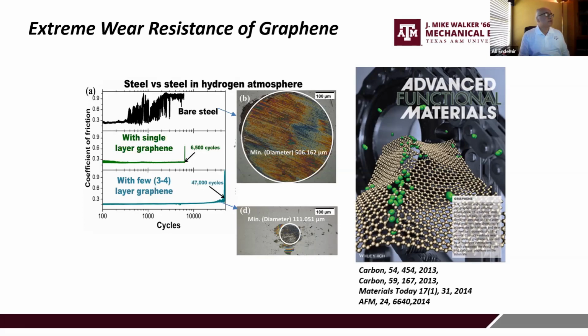These graphenes could be produced using the CVD method. Even one layer of graphene, under some reasonably high contact pressure, could last over 6,000 sliding cycles. If you build a few additional layers, that wear life would go all the way up to almost 50,000 cycles, which was quite remarkable.